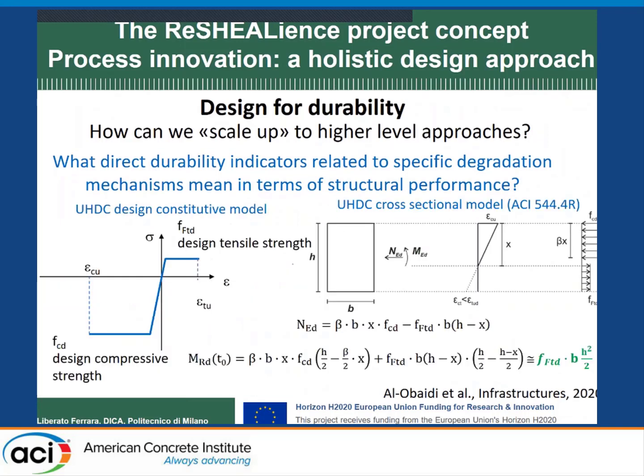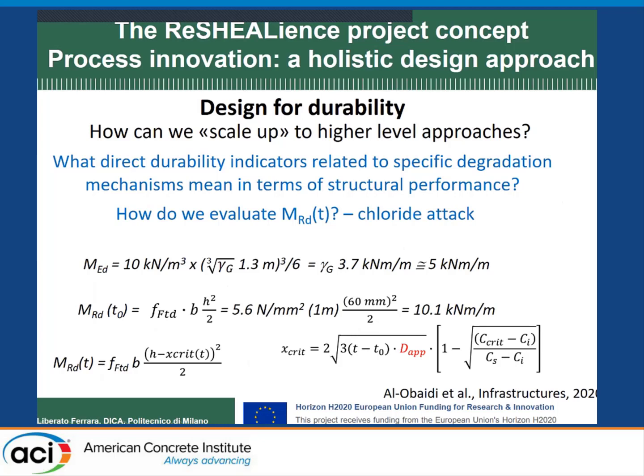How did we design the moment capacity? We followed the Eurocode, the FIB or the ACI 544 for our approach. So we use an elastic plastic approach in tension and also in compression with very simple force and moment equilibrium equations. And we were able to calculate the resistant capacity. You can see just some numbers to reflect. Compared to 5 kilonewton meter per width of 1 meter, which is the acting bending moment, we can guarantee a resistance of about twice as much.